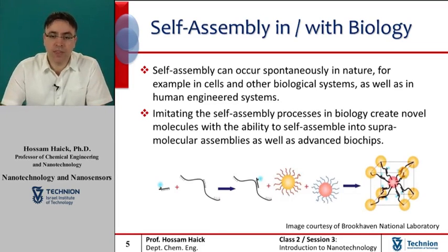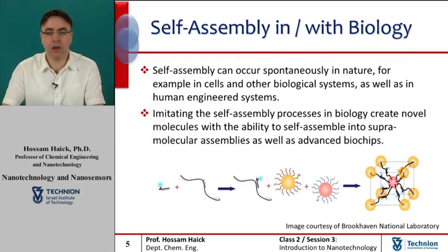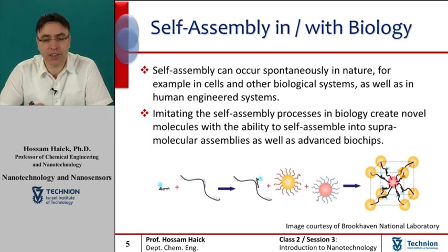The internal part of each DNA was encoded to recognize a complementary strand chemically bound to a fluorescent dye molecule. This setup resulted in a self-assembly of a three-dimensional body-centered cubic crystalline structure with gold nanoparticles located at each corner of the cube and in the center, with dye molecules at defined positions in between them.